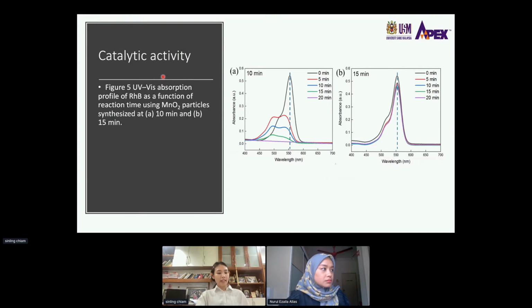The catalytic activity of the MnO2 particles was investigated by assessing their removal efficiency towards RhB dye. Both characteristic peaks decrease with time. The characteristic peak for the MnO2 particles synthesized at 10 minutes reduced at a faster rate compared to that at 15 minutes.